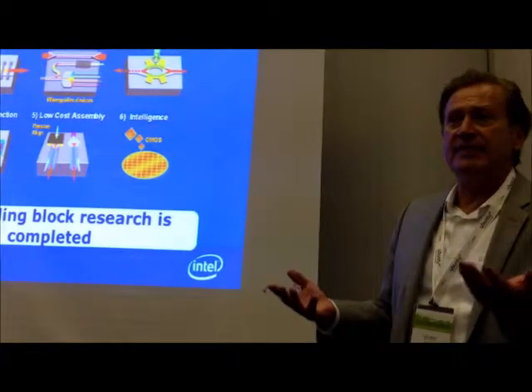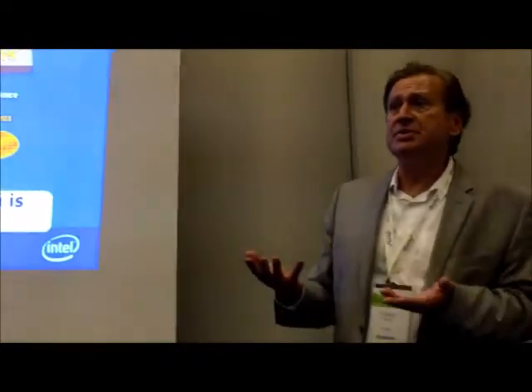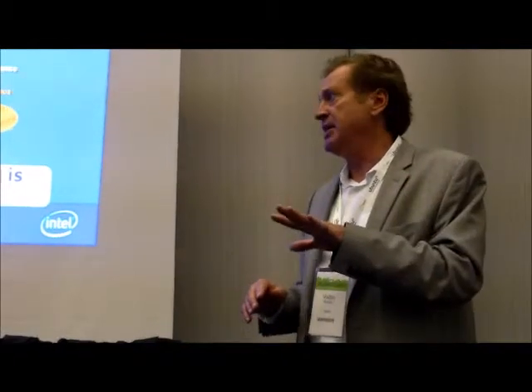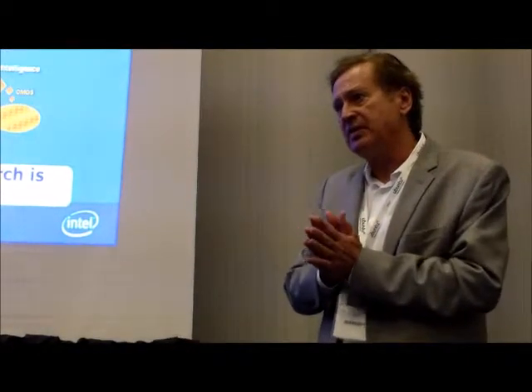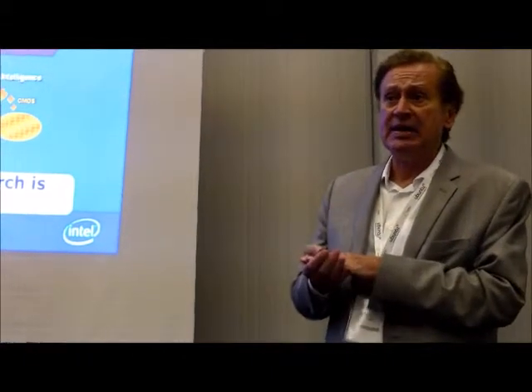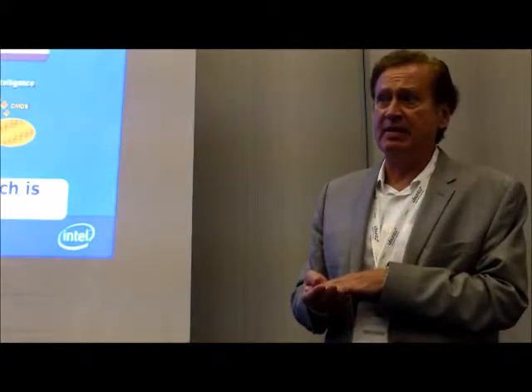We jokingly say if you put enough electricity across it, it will emit light — along with some smoke — but it won't laze. So one of the things we had to do is create something called a hybrid silicon laser, where we took waveguides — indium phosphide acts as the gain medium — and we put a small bar of indium phosphide over it. We had to figure out a way to bond the two together; the gap between them has to be on the order of 10 angstroms. That was a four-year project just by itself.